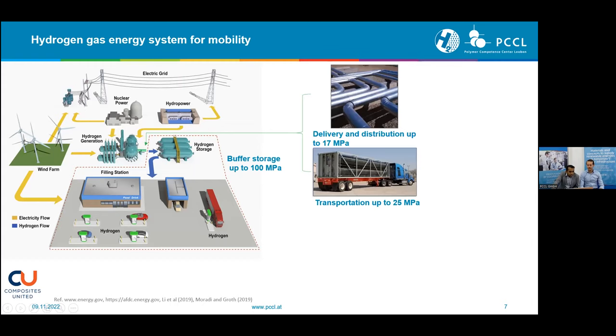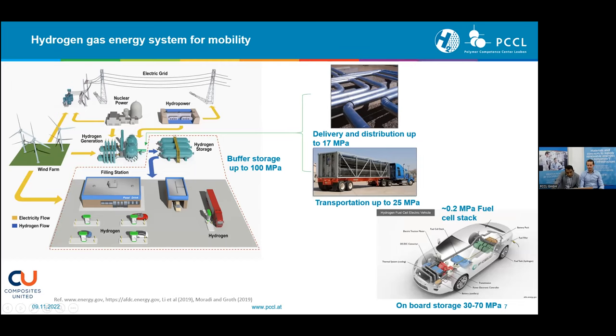And then when we consider the delivery of hydrogen from synthesizers to buffer storage, we have several methods like pipelines, as you see here. They normally work up to 17 megapascal, and also tube trailers, which are normally up to 25 megapascal. But when we consider the fuel cell vehicle, then onboard storage should be around 30 to 70 at the moment. But for the actual fuel cell, the gas should go in at a very low pressure. So therefore we need to have a lot of components in between to address all these conditions that we need.